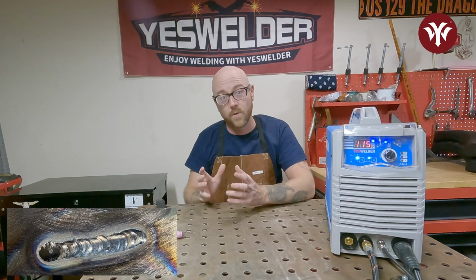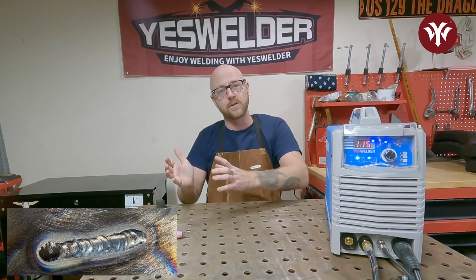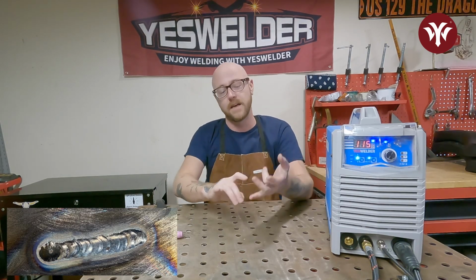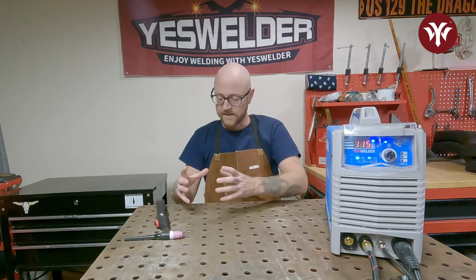So as you can see, I settled on 115 and the puddle flowed a lot better. It's always going to take a little bit of time to get the puddle created when you start a weld. However, once you get that puddle going, it doesn't matter if you're welding TIG, MIG, or stick. Once that puddle's going, you want it to flow nicely, but in a controlled and predictable manner. And that's how you know you have your amp set right.